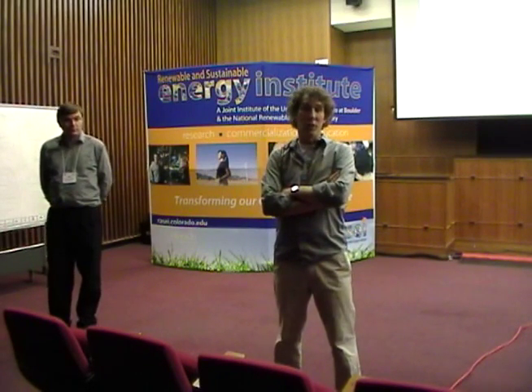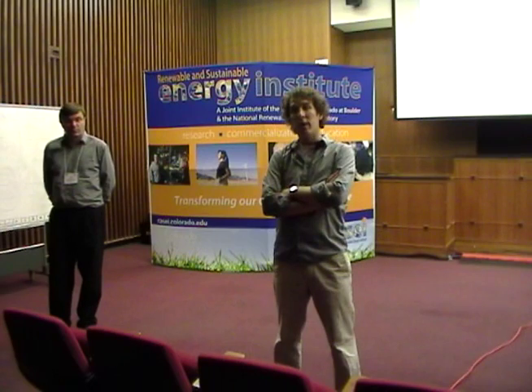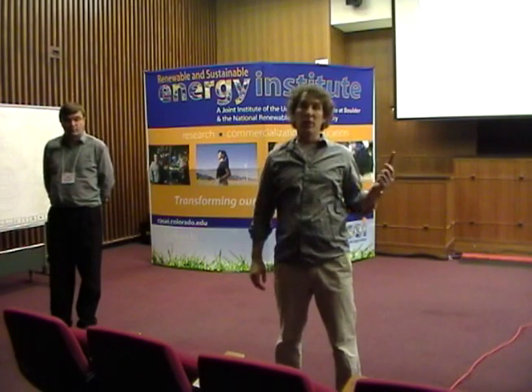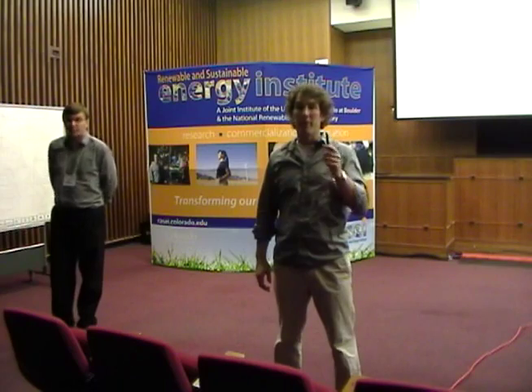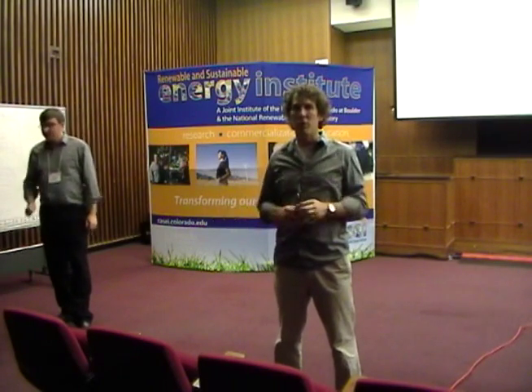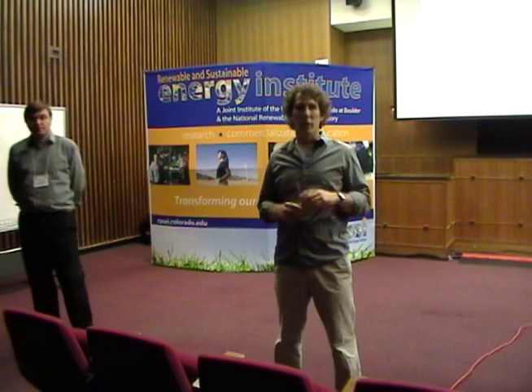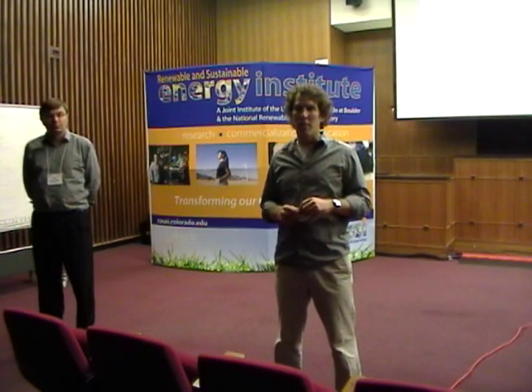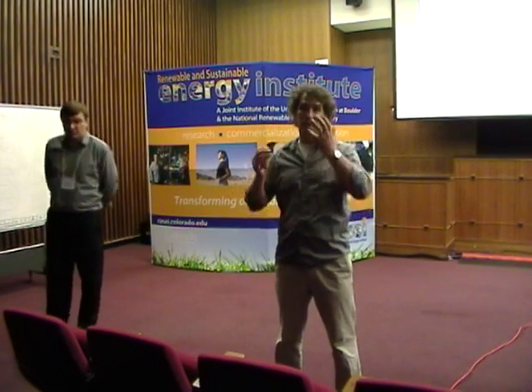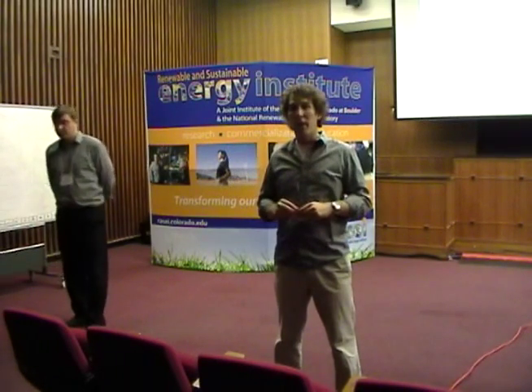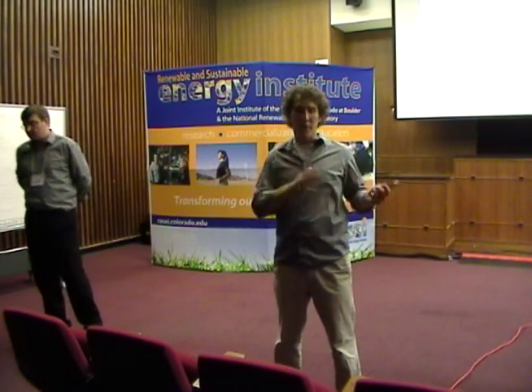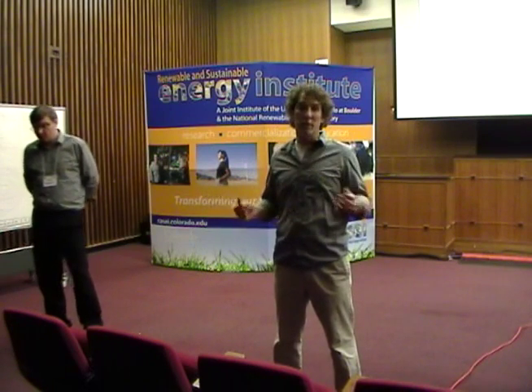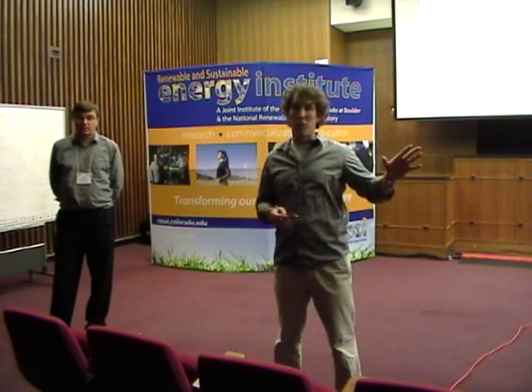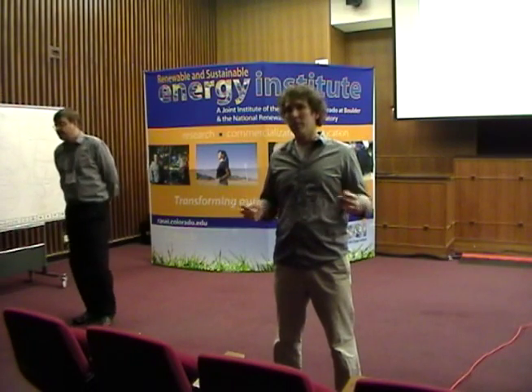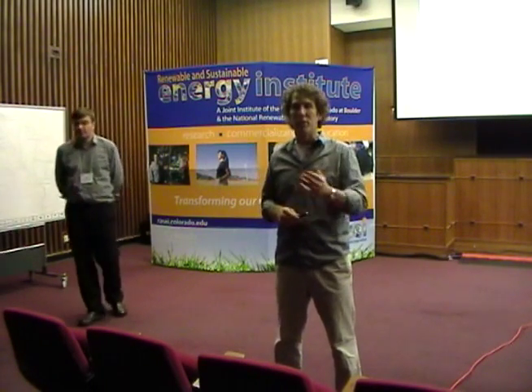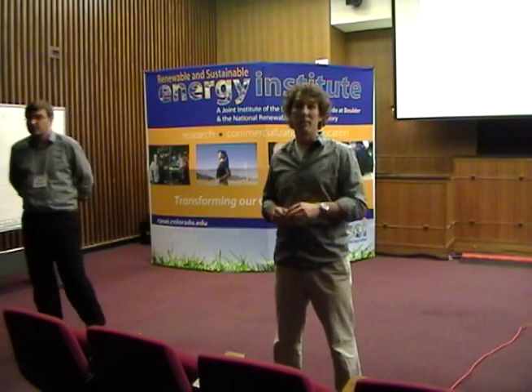It's probably difficult to integrate into the growth systems that we use. Most of these cells are grown by metal-organic vapor phase epitaxy, chemical vapor deposition. And graphene has a different lattice constant. I don't know a lot about graphene. I'm just guessing that it's crystalline rather than amorphous, and putting that in the same system is going to wreck your material. That's not to say that there may not be other growth systems that are compatible. So that's probably the best I can say, is that it's not easily integratable.